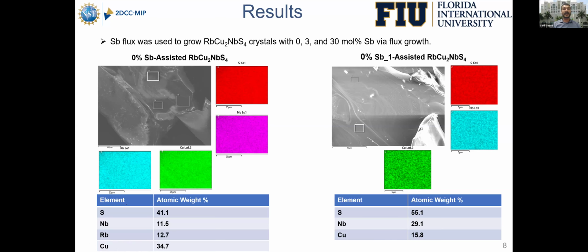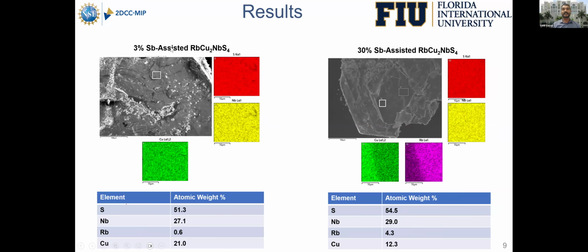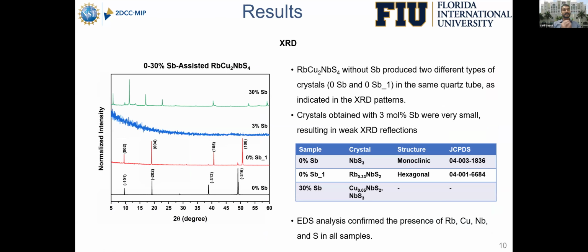Moving forward with the higher doping concentrations, 3% and 30% antimony assisted rubidium copper niobium sulfide, you can see all the materials are uniformly distributed, and the atomic weights for sulfur, niobium, and rubidium copper change with the different antimony concentration. Based on this, I did the XRD, and interestingly, as I mentioned, there is a different type of XRD pattern for 0% SB and 0% SB1 inside the same quartz tube.